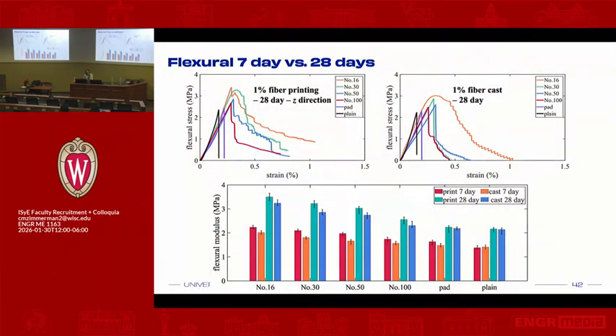And one thing with concrete is that it introduces a new variable, which is that it does not really complete its process of solidification until 28 days. So the result that you get in 7 days could vary drastically at 28 days or 50 days. So there's an aspect of prediction, based on the parameters or the properties that you see at the start of your print, and at 7 days, 30 days, 50 days, to be able to predict whether that's going to be a solid, structurally sound structure.